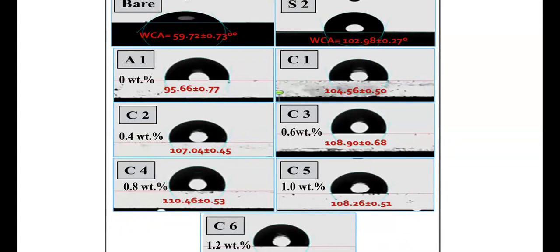So we have chosen S2 as the best coating binder system, and now we introduce nano calcium carbonate into it, and we see the water contact angle measurements. When we introduce the nano calcium carbonate, the water contact angle tends to increase, so the hydrophobicity tends to increase further. With 0.4 weight percent of nano calcium carbonate, the hydrophobicity is increased to 107.